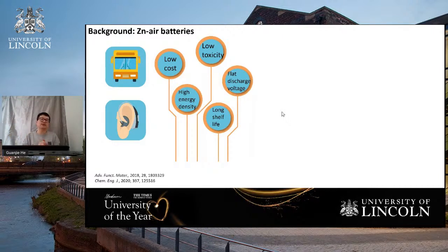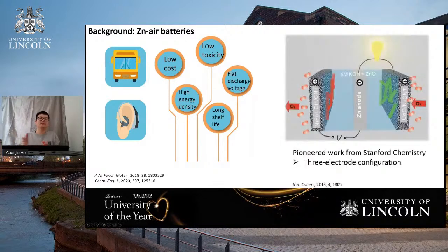So how can we realize rechargeability? One pioneering work from Stanford developed this 3 electrode configuration. During the discharge process, they connect the zinc anode with the oxygen reduction catalyst. They use cobalt oxide on nitrogen doped carbon nanotubes for the oxygen reduction process. But during the charge process, they connect the zinc anode with the oxygen evolution catalyst. They use nickel iron layered double hydroxides on carbon nanotubes as the oxygen evolution catalyst. And this 3 electrode configuration can realize the charge and discharge process for zinc batteries.